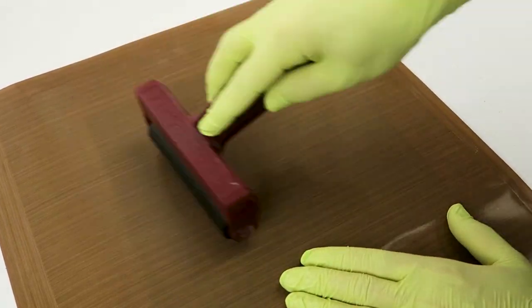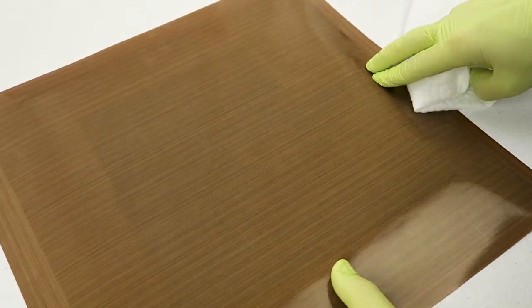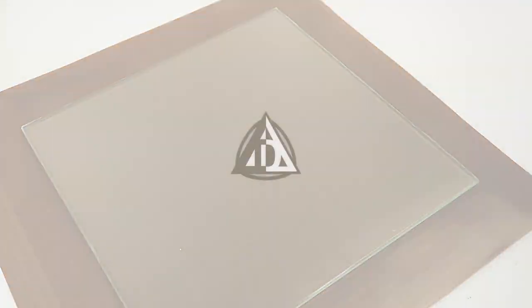But this does remove all the bubbles very thoroughly and create a completely void-free sheet when working with woven carbon fiber. Now with forged carbon fiber, it's a bit more prone to pinholes, so even with the rolling, you may still get some pinholes in that. But with woven carbon fiber, it's a pretty great technique.